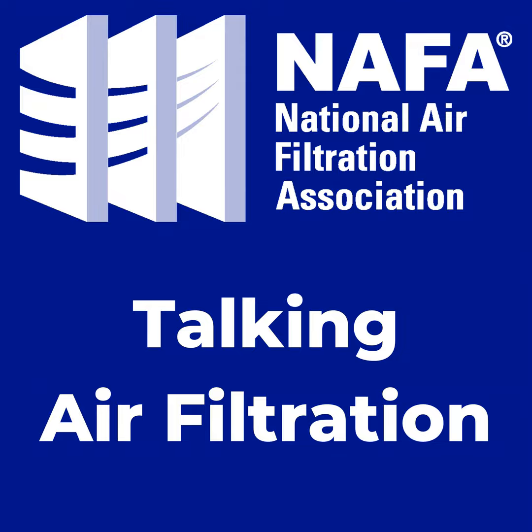And then I baked that glass slide in a furnace at, I think it was around 600 Celsius. It converted those polymeric fibers into indium tin oxide ceramic fibers, and it kind of made a coating on the glass. And then I was testing the properties of it there. So you could see it made the fibers transparent, and then I could get electrical current to flow between the electrodes that I painted onto that slide.